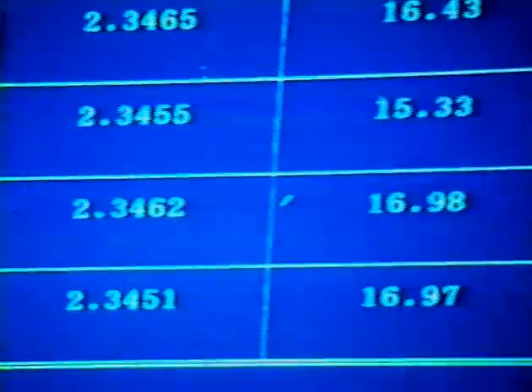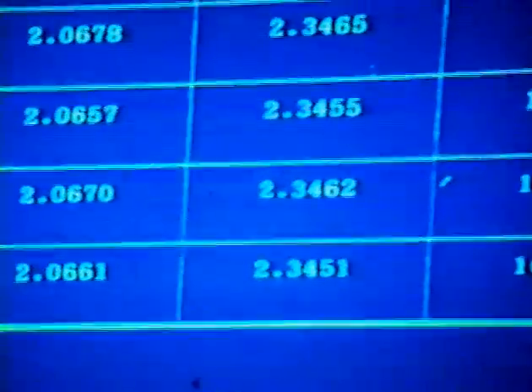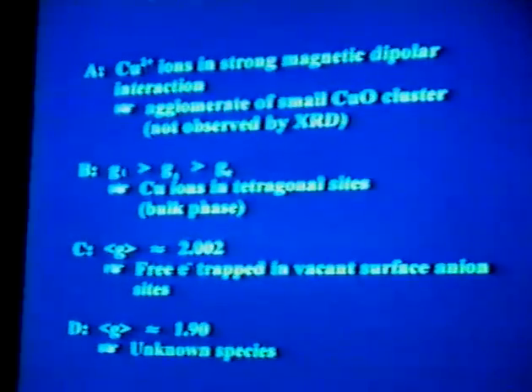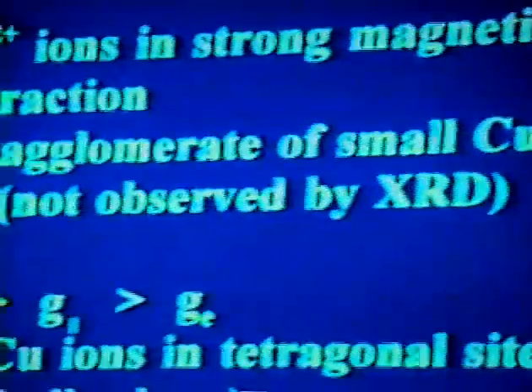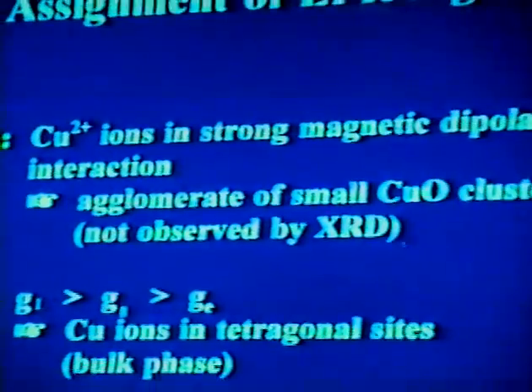From here, the perpendicular g component and parallel g component seem to have nearly no change, as well as their hyperfine constant. And furthermore, the g parallel component is larger than the perpendicular component, and larger than the free electron g value. So we can think that the signal B is really a monomeric copper species in the tetragonal site. This is a partial assignment for the EPR signals. The signal A probably comes from a stronger magnetic dipolar interaction, so it will grow and finally become a small copper oxide cluster. However, it could not be observed by XRD.